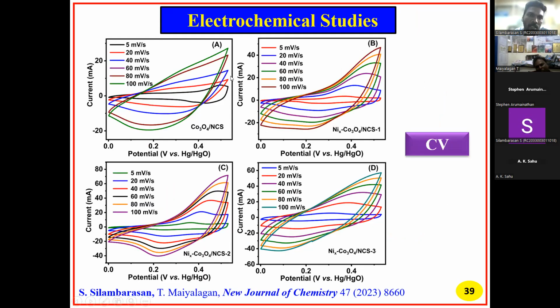Next, the electrochemical studies in CV, cyclic voltammetry. Here, in the CV with a three-electrode system, they applied scan rates from 5 millivolt per second to 100 millivolt per second. They applied a potential from 0 to 0.55.